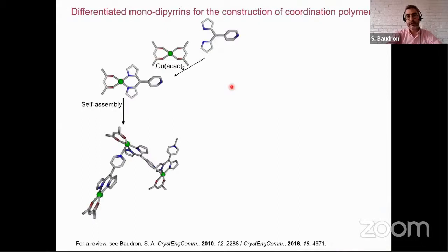For example, if one considers the dipyrrin bearing a pyridyl group in the position 5, assembly with copper acetylacetonate leads to the formation of this type of heteroleptic compounds with, on one end, an acetylacetonate, a dipyrrinato on the other end, and a pendant pyridyl group. Upon self-assembly, this type of compounds does form a one-dimensional coordination polymer by coordination of a pyridyl group to a